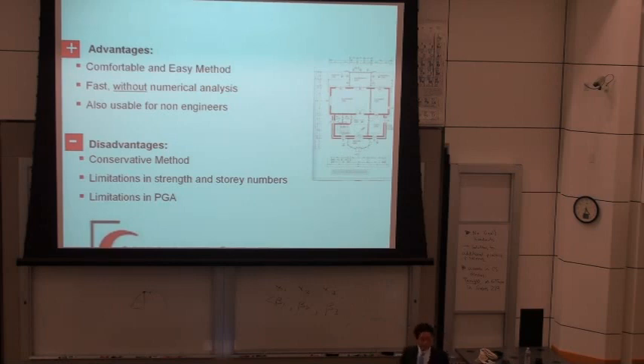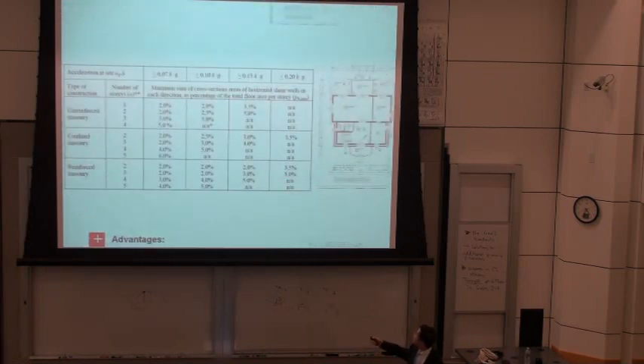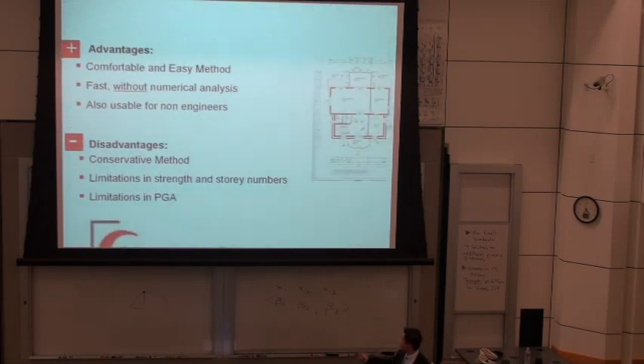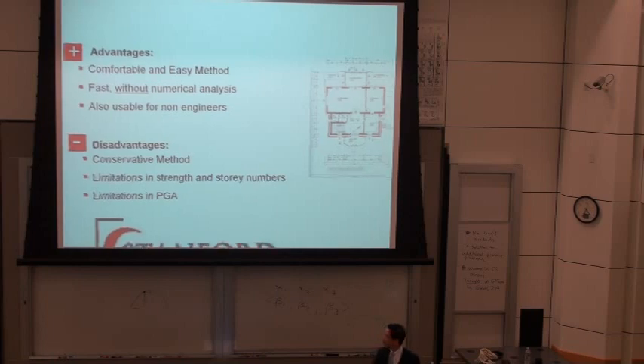The disadvantage is that it is a very conservative method, which is clear. It gives you limitations in strength and story numbers. On the slide before, you can see you have also the story numbers you want to have. If you want to go above these story numbers, it's not allowed to use this table anymore. Or if you want to go above these PGAs, in this case, it's not allowed to use it anymore. Or if you have less than these shear walls in your structure. And as I said, limitations in the PGA.